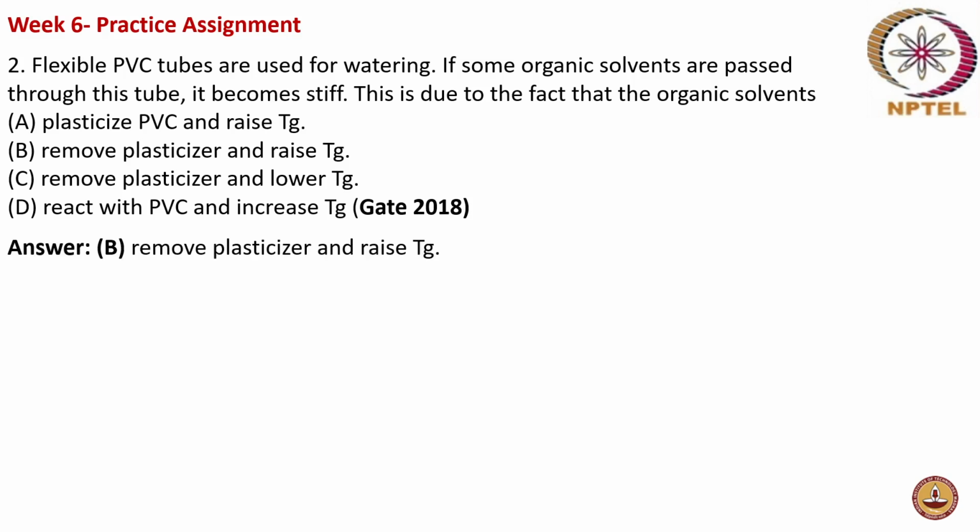Now let's see the answer. It's actually remove the plasticizer and it raises the Tg. What happens is that the plasticizers get dissolved or diffused into the organic solvents, and then the Tg is raised.